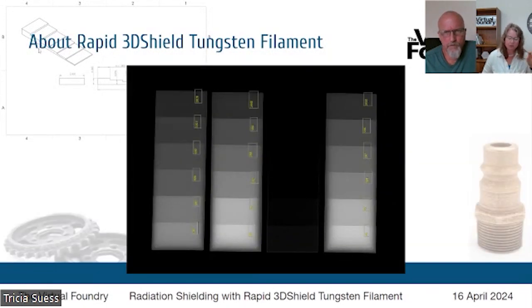This is that 450 kilovolt test result. It's using the same test shape. Looking from left to right, the leftmost image is 3D printed Rapid 3D Shield Tungsten Filament. The next image is that same machined lead. The next, the blank space, is actually not blank. It's that same shape, but 3D printed with our copper filament. That material was also included in these tests. The last image on the right, again, is lead.